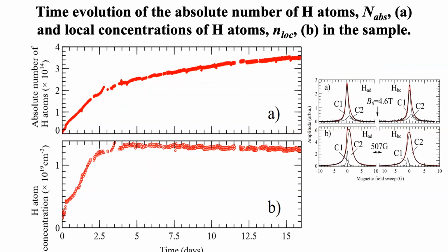Also, knowing that the line width determines the concentration, seeing the shape of this signal, we understand that we have two different regions of hydrogen in our sample: one region with high concentration, which corresponds to the broad line, and one region with low concentration, which corresponds to the narrow line.